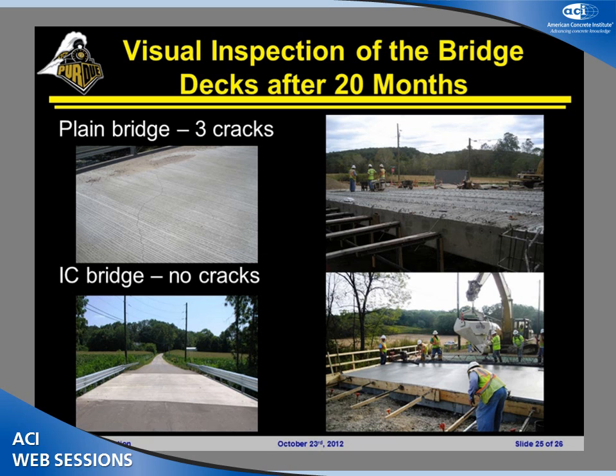Now, the strength of the plain system was again about 10 to 15% higher. The transport properties of the internally cured system are slightly lower in that system. They're about 10% lower. But what's really driving us to the idea that this has the potential to change service life is what we observe going back to this bridge deck as we keep going throughout time. The plain deck has 3 cracks that are formed, and the cracks, I would say, are substantial width. The internally cured deck has no cracking.